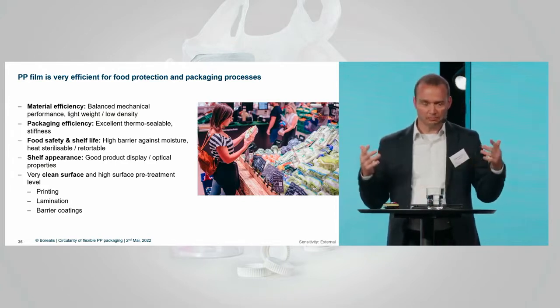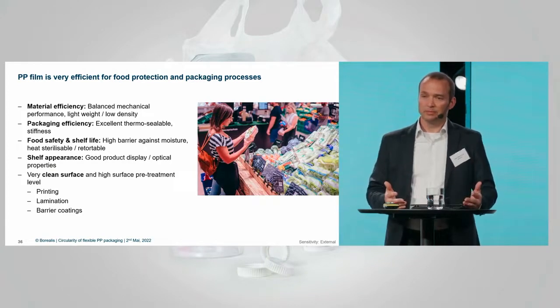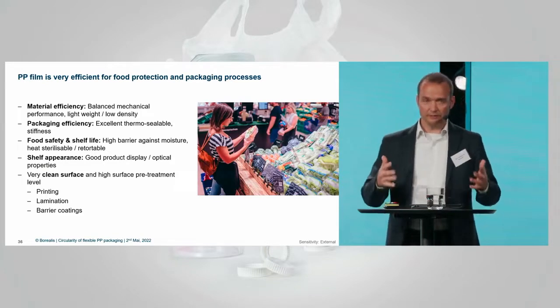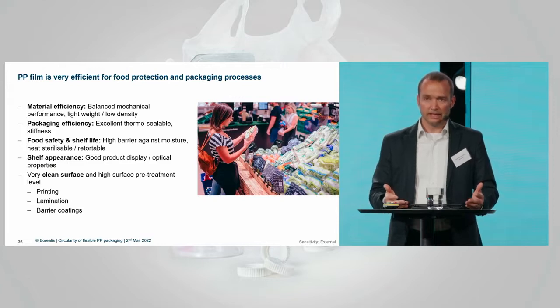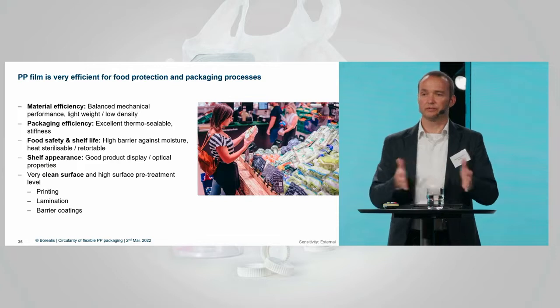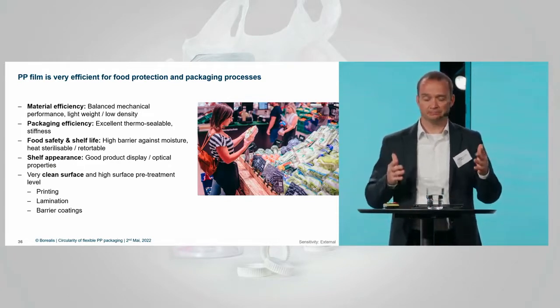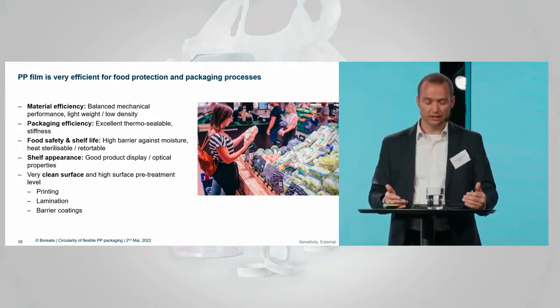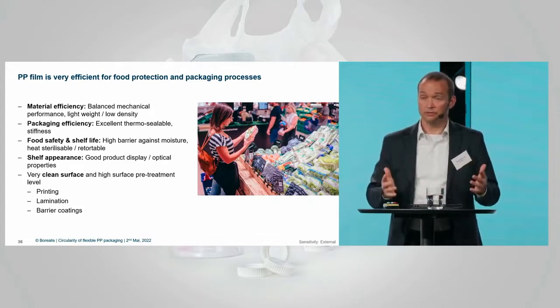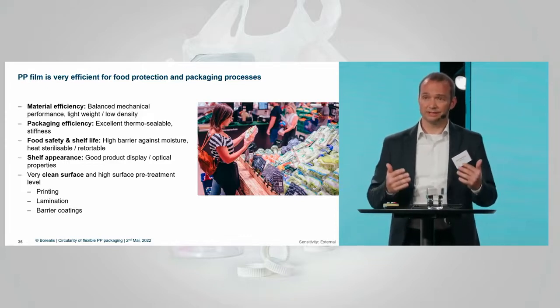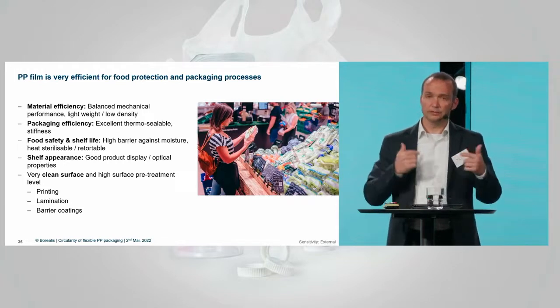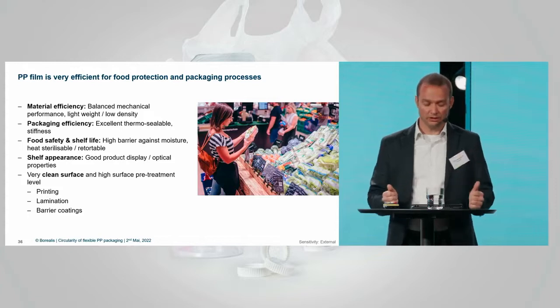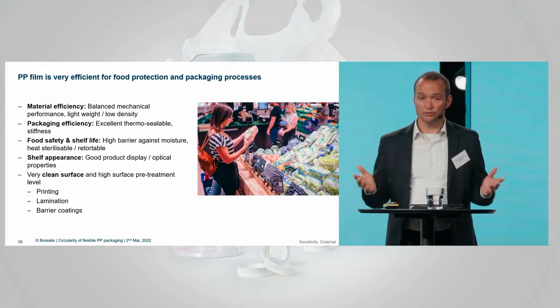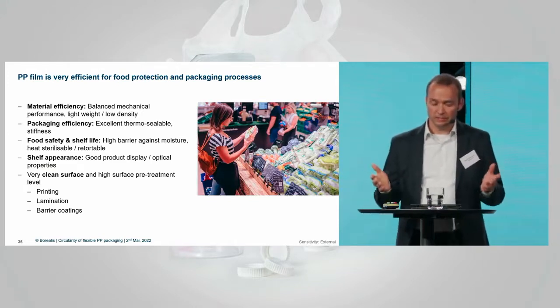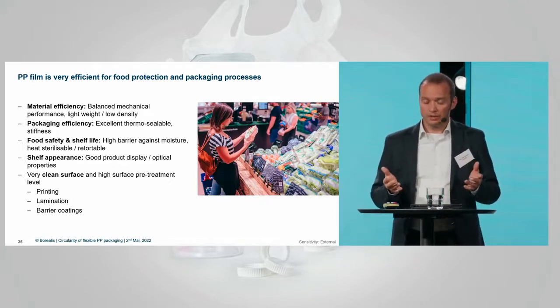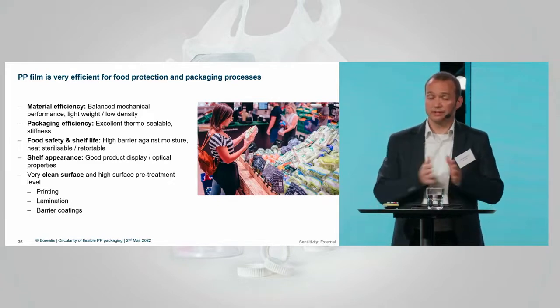So, of course, I was now telling about the benefits that we have with polypropylene in flexible packaging, but we also still have an issue today, and this is when we look at how much is actually recycled. In general, there is an issue when we look at the recycling rate of plastic packaging. We do have the recycling quota, the target that by 2025, for instance, across all plastic packaging, we want to have 50% recycled, and in 2030 even 55%. Unfortunately, we are still far away from that. And it is even more a problem for flex packaging, but also for PP flex packaging. The reason is that it depends, of course, on the geographic region, but in some areas it's either not collected, or it goes to landfill or incineration. So it's not ending up at the recycler.